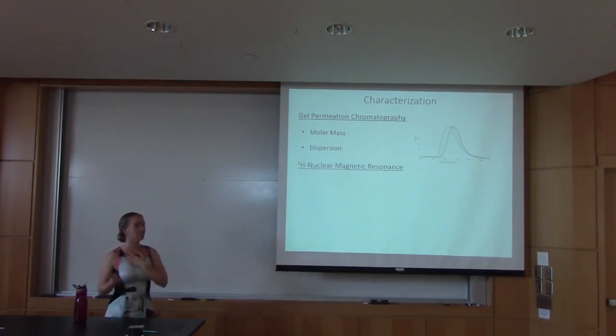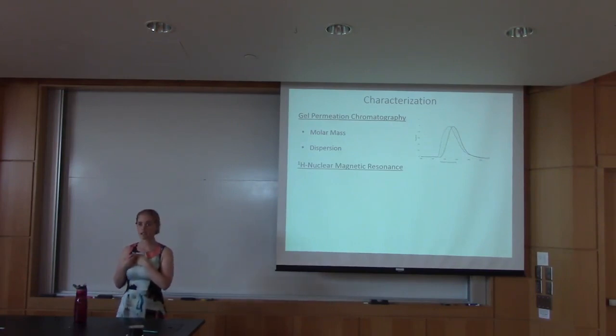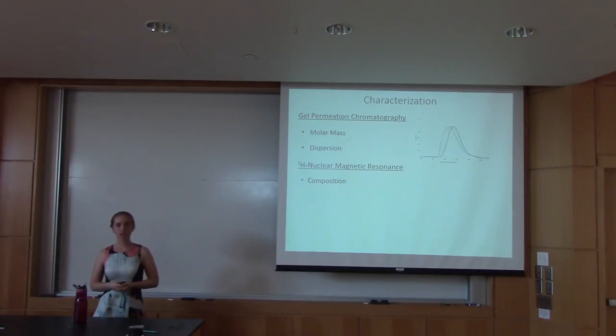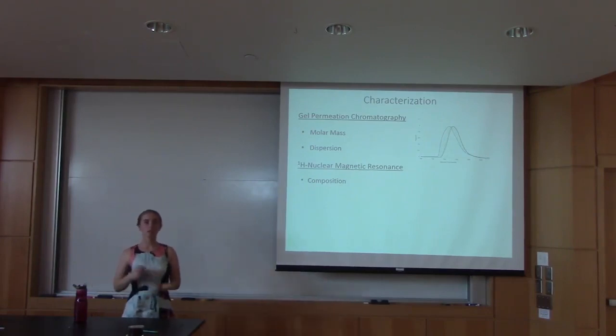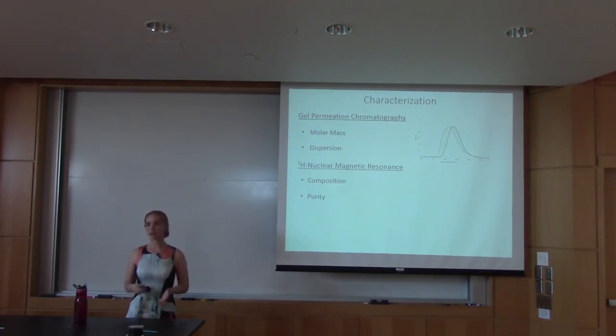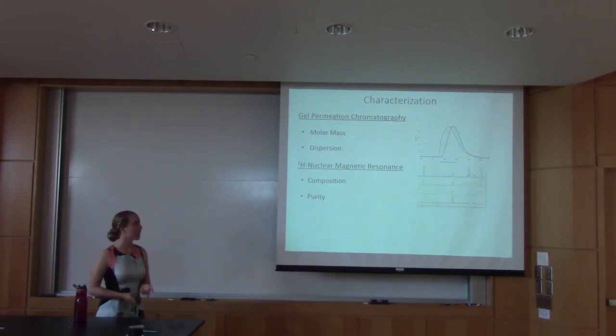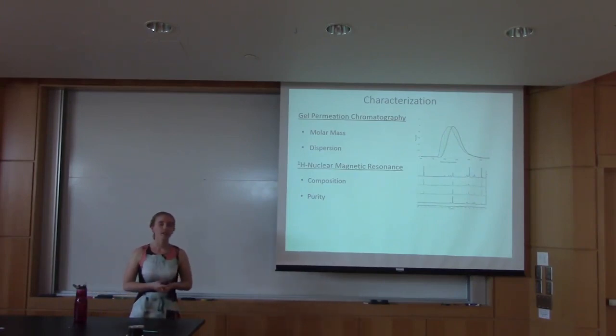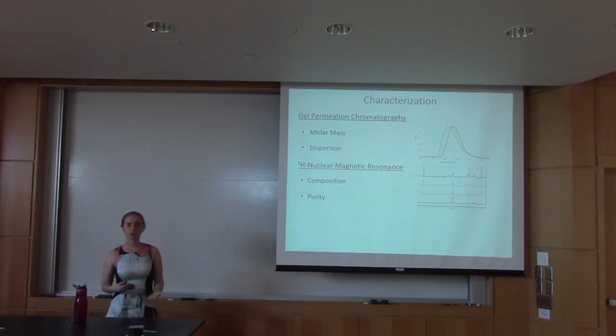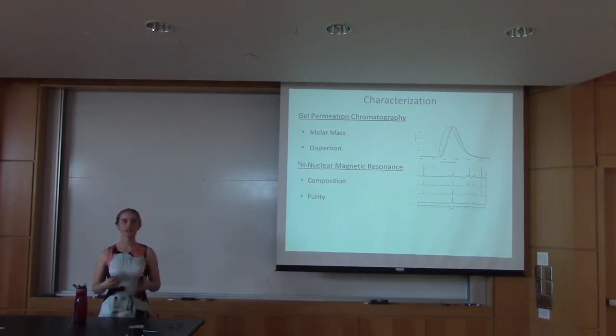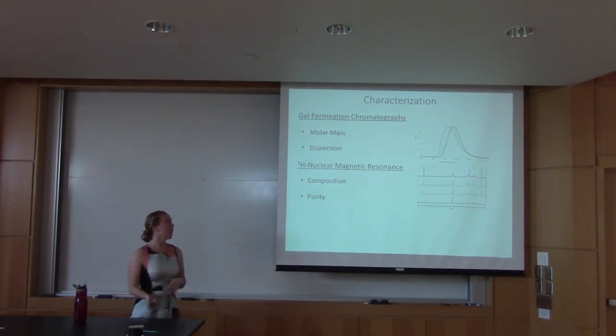And then we also did hydrogen nuclear magnetic resonance, or HNMR. This tells us about the composition of our random copolymer. So did we make what we wanted to make, as well as the purity of it. So were there any weird side reactions that happened that we didn't think would happen, and how prevalent were they? We get some data that looks like that. What these first two are doing is just confirming that we made what we thought we wanted to make, and just seeing what exactly is there.